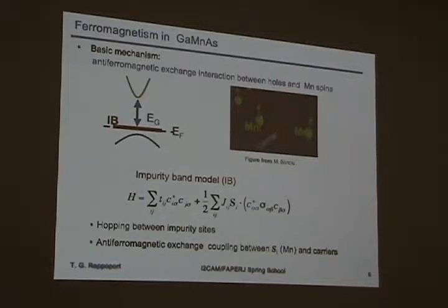It means that a paramagnetic DMS has very low manganese concentration. It's from a 3-5 family of semiconductors, or it can be from a 2-6 family of semiconductors, the old ones from the 80s. They are normally paramagnetic, even when they have the manganese incorporated.